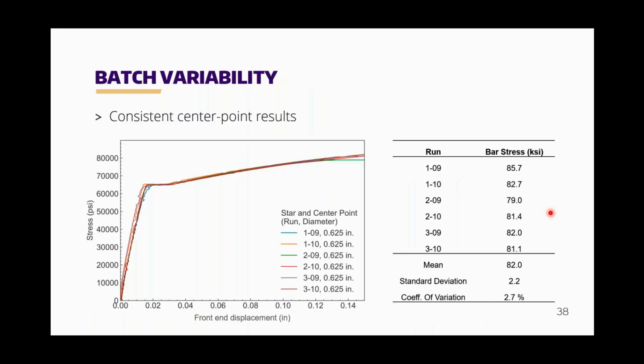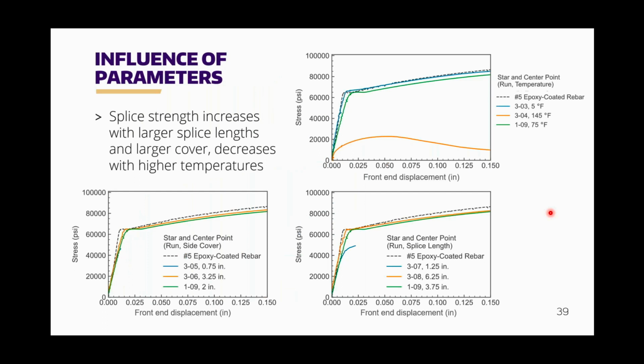One of the strengths of this experimental design is that you are able to look at these replicate specimens and determine the batch-to-batch variability. The hope is that that's small, and then you can use the entirety of the results without having to do any normalization. And that's what you see here. As Carolyn showed in the bar chart at the beginning, this stuff has very repeatable properties, and we saw that again with these results, with a coefficient of variation of about 2.7%. You can see the curves on the left, stress versus front end displacement, and they are very, very consistent. That gave us confidence that we would be able to combine the results from all three batches of material into one statistical analysis.